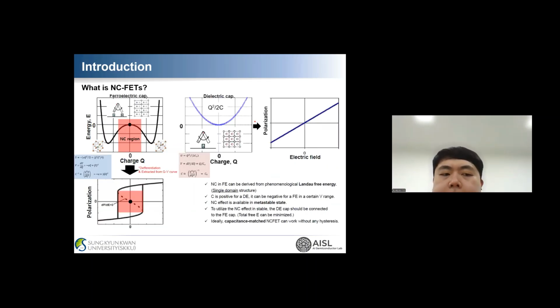A negative capacitance FET utilizes the negative capacitance behavior of ferroelectric under a certain voltage range, enabling low power transistor operation. This negative capacitance typically exists in a metastable state, and is stabilized by connecting a dielectric layer through capacitance matching. By forming a ferroelectric dielectric stack, the unstable ferroelectric can be stabilized, resulting in an increased effective capacitance compared to a single dielectric layer.